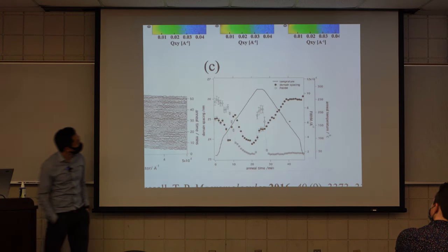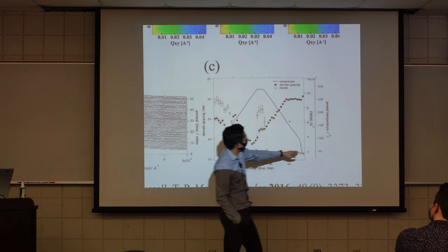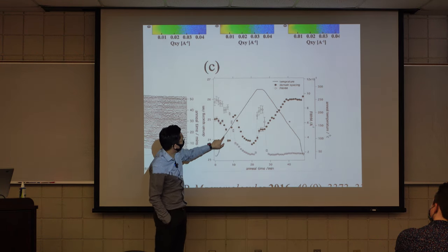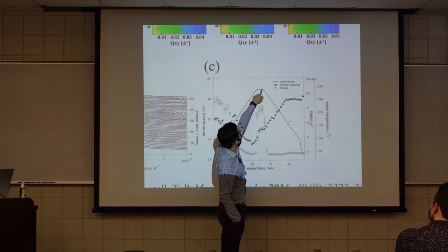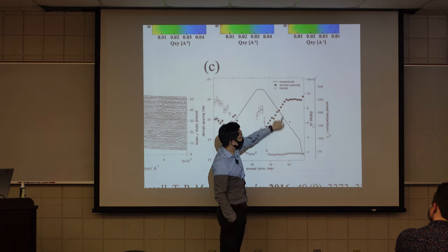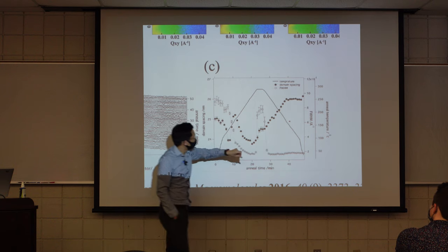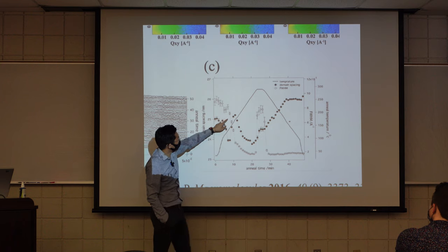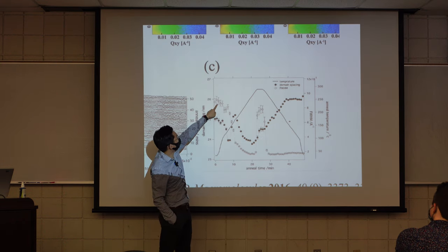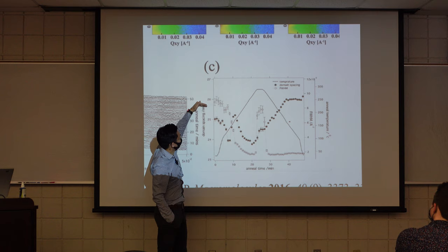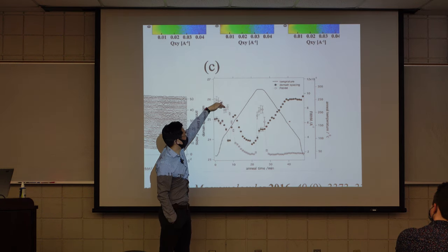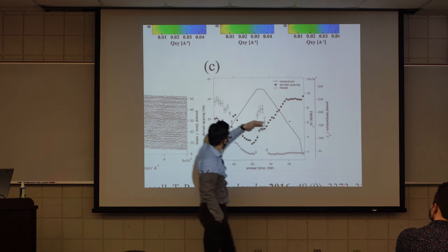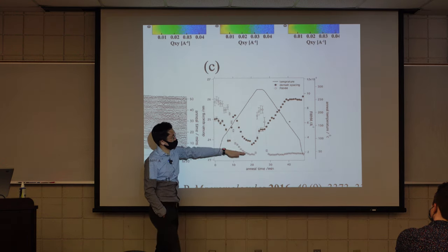right here. If we look at this temperature profile, this is the solid line. We can heat the sample up, cross the order-disorder transition, stay there, then go back. Interestingly, your domain spacing pretty much follows what you showed before. But more importantly, let's look at the full width at half max. The annealing needs to reach a certain temperature to order, as you showed. This is a high value of full width at half max. When the ordering happens, this drops pretty rapidly.